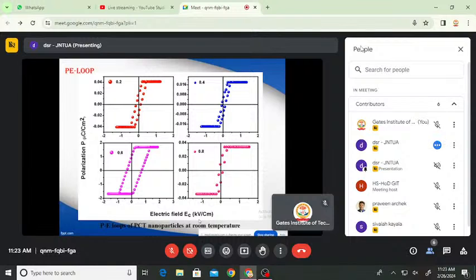From this PE loop, the saturation polarization, coercive field, and the remanence polarization of the lead cobalt titanate particles have been studied. The values of ferroelectric parameters expressed that the saturation polarization was shifting to 1.74 microcoulombs per centimeter square from 0.042 with rising Co composition. This type of random variation of PS is due to quick and partial response of charges for the input field frequency. The coercive field as a function of composition was also shown. This coercive field was observed to be changing for all the Co doped lead titanate nanoparticles.